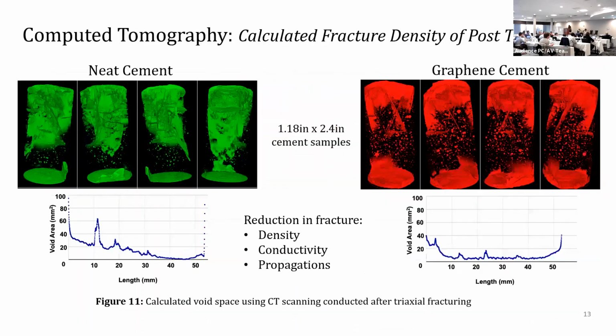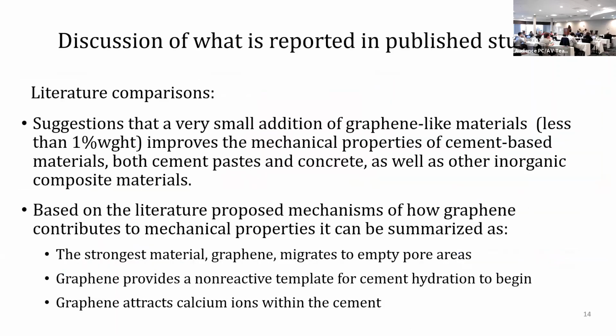So where from there? Okay, we have these samples, they fractured in the triaxial test. We pushed them to the limit, and now we wanted to see how these fractures look. Does the graphene really make any difference or not? So you can see neat on the left and the graphene enhanced cement on the right. The volume of the fractures and their connectivity is really disrupted by graphene. So I would say thumbs up on this one. But there is still much more work to be done.